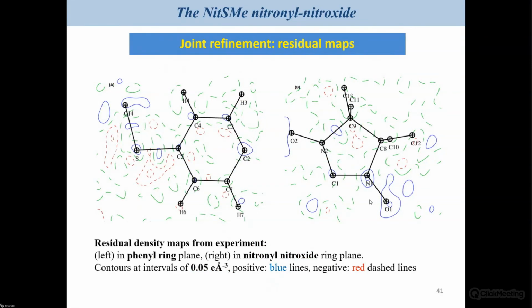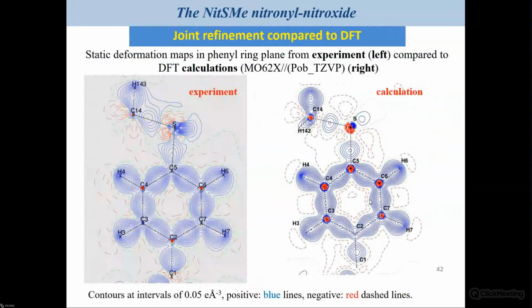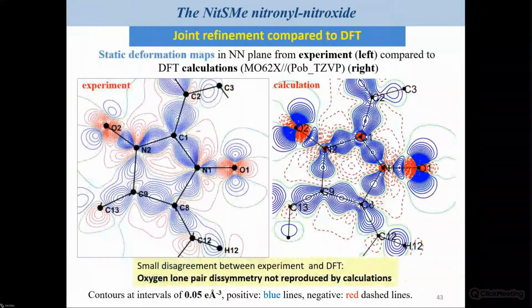Now, if you just want to have an idea of the quality of the joint refinement, you see the residual maps obtained for the total electron density, and they are very clean. And the model you obtain by your experiment is very close to the one predicted by calculations. So again, it means that everything is okay.